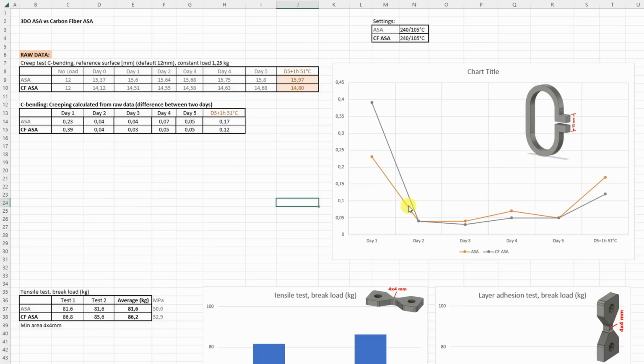These are in millimeters. If there would be, I don't know, PETG, it would be 5 or 10 times bigger on the scale. And basically after 1 day it stopped with deformation, and even 1 hour at 51 degrees Celsius resulted in very minimal additional deformation.